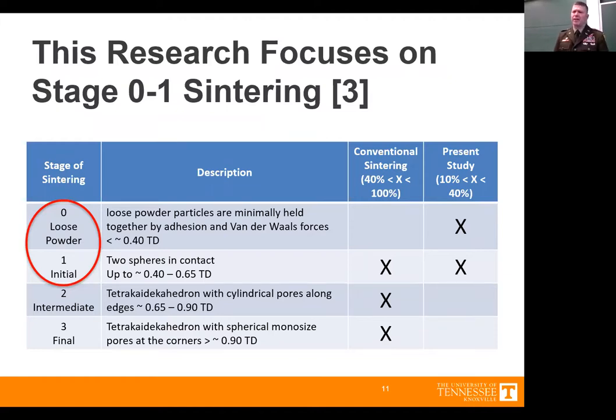Again, this is just the same information presented in a slightly different way. It points to some of the descriptions between stage 0, or loose powder sintering, and stage 1 sintering. Intermediate and final stage sintering are more associated with industrial processes. When you talk about the sintering of ceramic nuclear fuel pellets, they are sintered to approximately 95 to 100% theoretical density. But that's done under very high temperatures, very controlled atmospheres, and usually lots of pressure applied either before or during the sintering process.